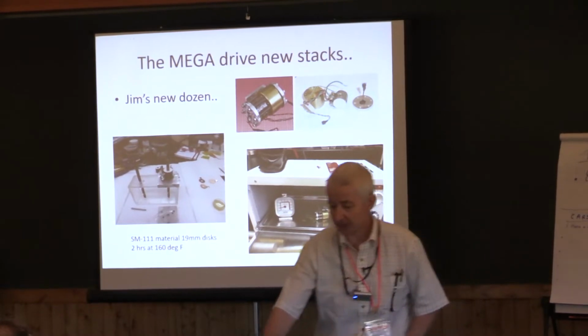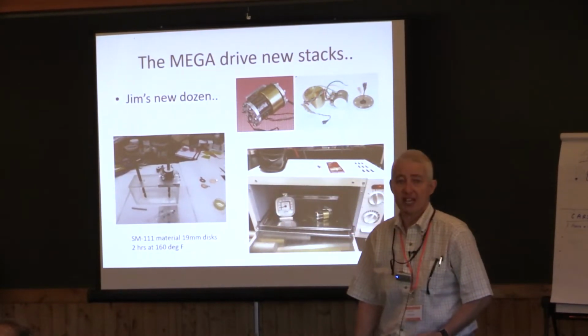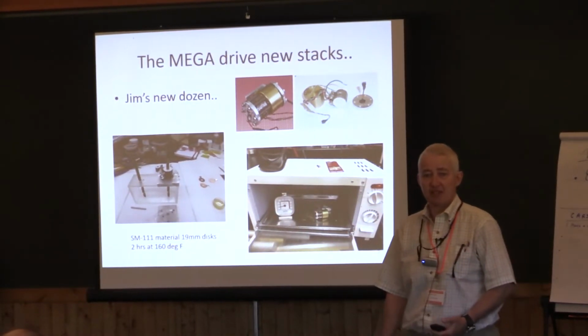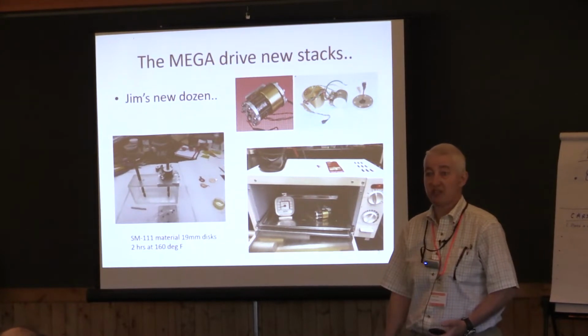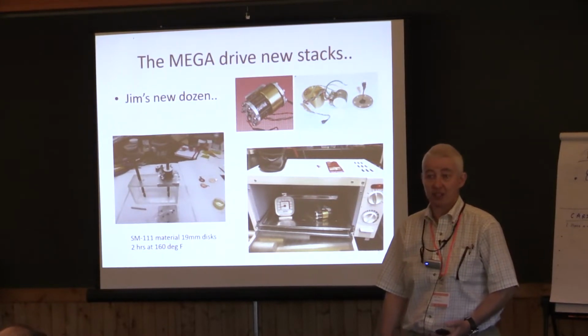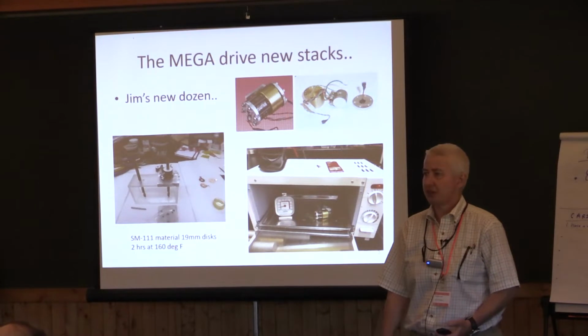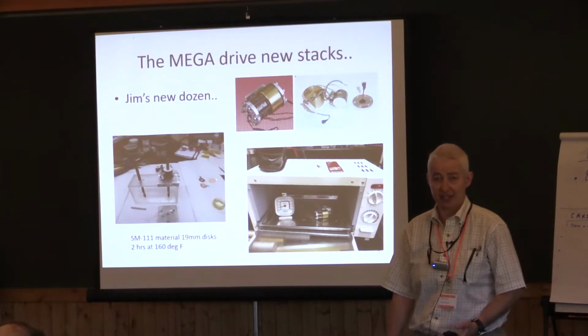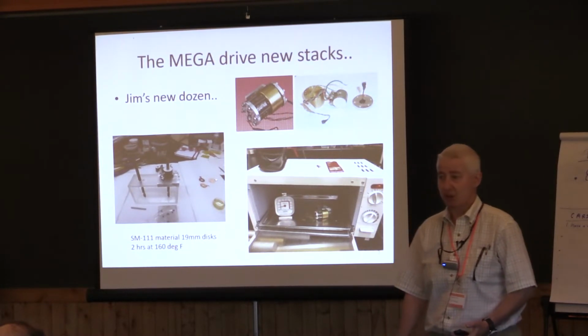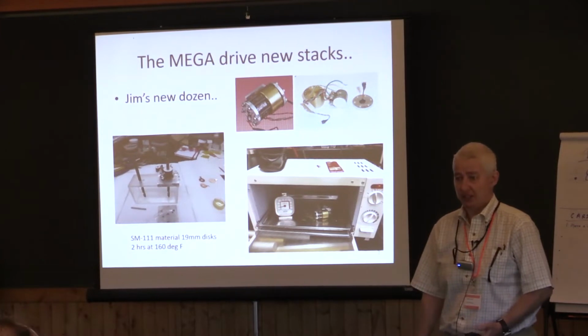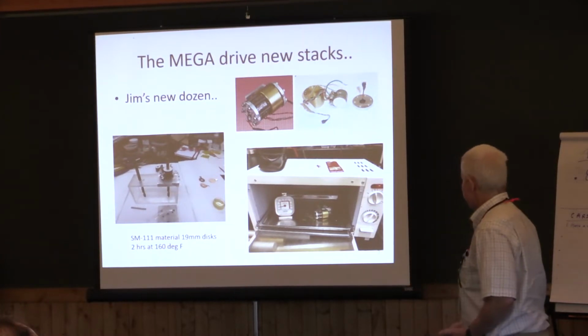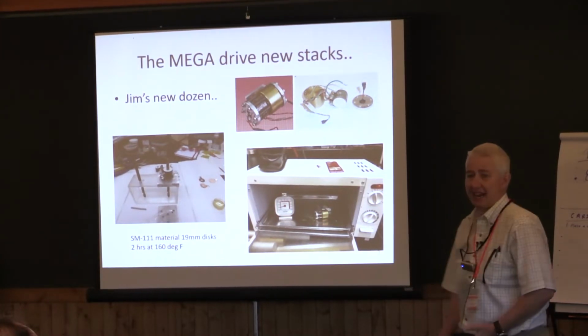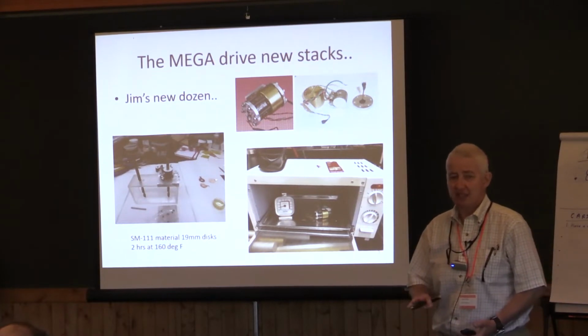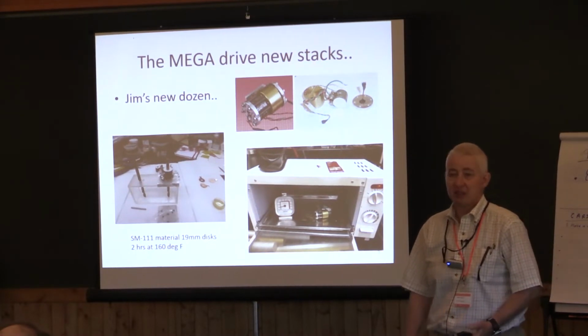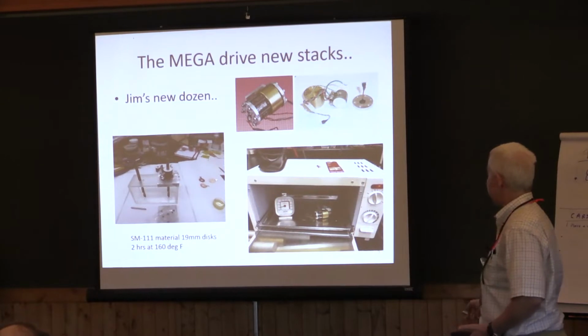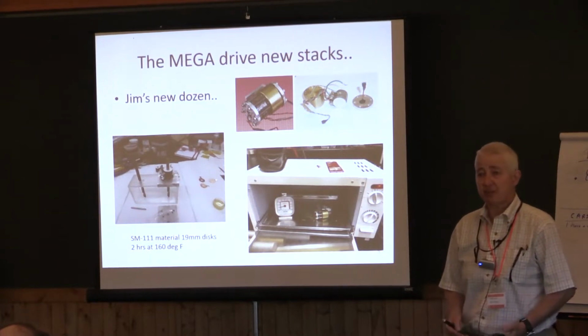So recently we looked up the specs for the epoxy agent, and it says you're supposed to leave it at room temperature for 24 hours, and then cure it for 2 hours at 212 degrees Fahrenheit. So that's nearly 100 degrees C. So we were way off on the actual curing temperature. That means that every time we built a stack, it always seemed to have slightly different properties. And we want these things to build arrays with, so we want them to have very similar properties.